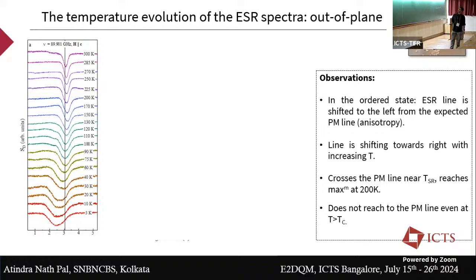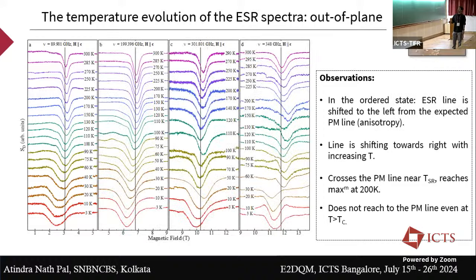Very interestingly, this is the temperature-dependent ESR spectra of FGT at a fixed frequency. This solid line is the paramagnetic line; if you don't have any anisotropy, it should follow this line. You can already see at low temperature there is a huge shift from this line, and at high temperature the shift is in the opposite direction. So the anisotropy is changing sign from high to low temperature, and this shift is happening near 120 Kelvin. Then if you plot other frequencies, it shows overall similar behavior.